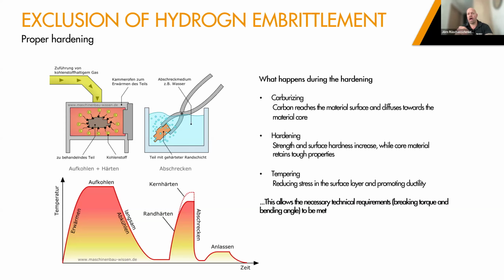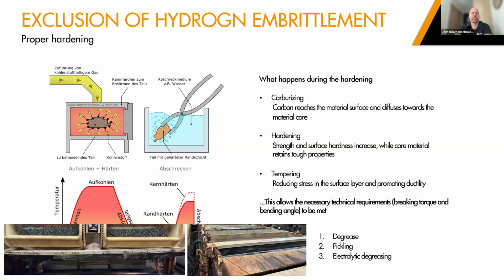The next thing, after this, we do HE testing, which I will show you 2 slides later. So we have 2 stages where we test for HE. First of all, after hardening. Secondly, after surface treatment, because you also can induce HE unwantedly during the surface treating phase. So the next step would be to go for the surface treatment.